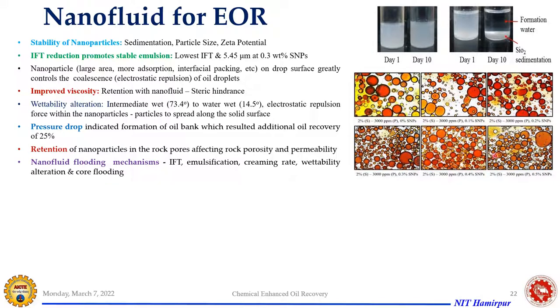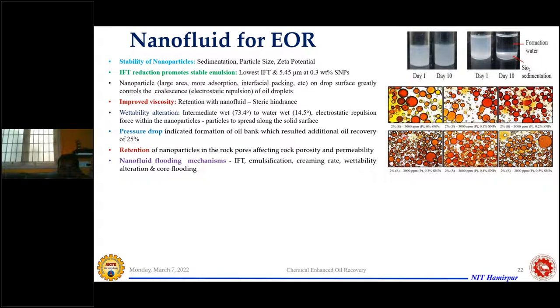and here you get a much larger number of droplets, a rigid, more stable kind of emulsion. So there is a synergistic interaction because of the alkali, the surfactant, polymer and nanoparticles, because of which you're getting a more stable emulsion film and emulsion properties.